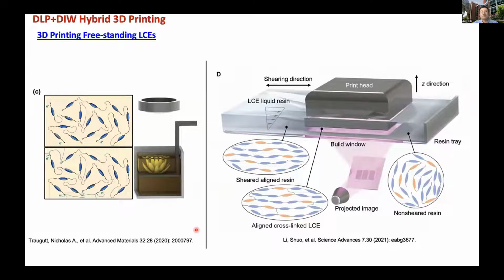DIW, like I said before, is the most used approach for printing LCE, and people also try using this DLP printing approach to print LCE. I think this work is done by Kevin and also Christopher Yakacki's group. But in this case, they're printing the LCE, but the LCE is not really aligned, so they're really using the LCE for energy absorption. And the other approach is by Rob Shepherd's group, and they're actually using this old DLP approach, the B9 Creators approach.